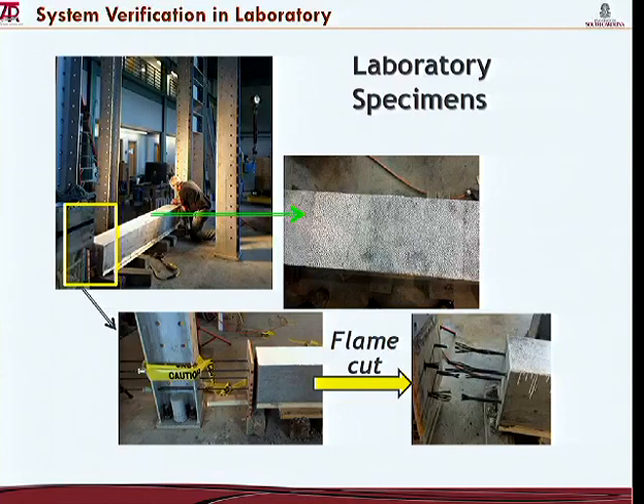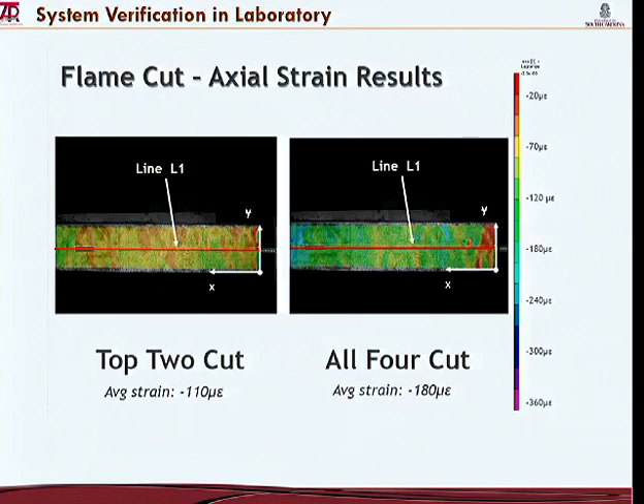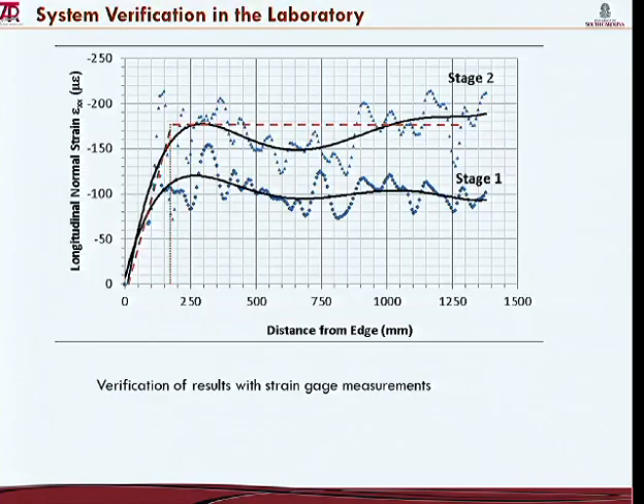We had to flame cut the strands, and these are the images that were obtained, where the top 2 strands were cut first, and then all 4 strands were cut. Average strain 110 microstrains in the first case, 180 in the second case. So here we're talking about real low strains. Now, if we plot the strain field along this center line, line 1 that is shown here, the blue dots or triangles show the strain results. The solid line is an average.